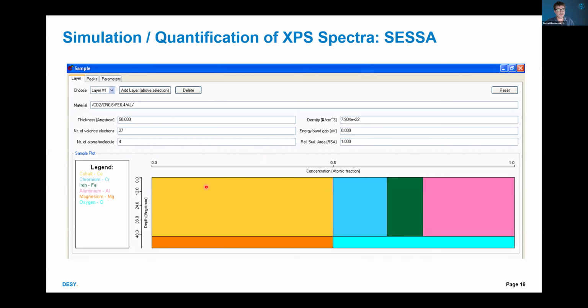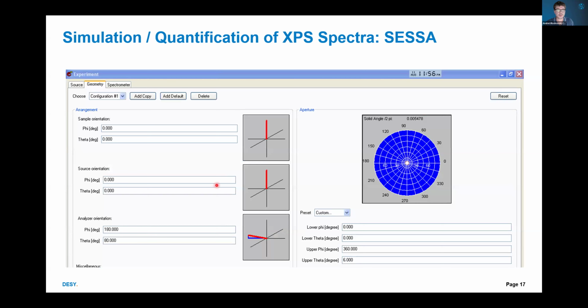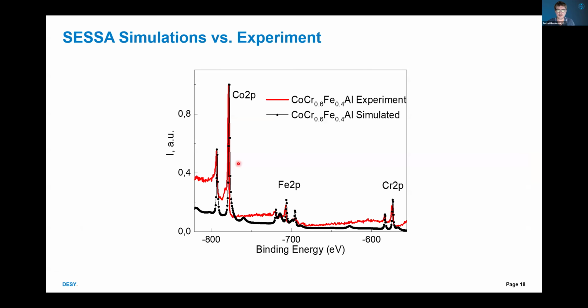As I told, the software, I think SESSA, is now freely downloadable from the NIST website. You can simulate very well the shape of the photoelectron spectra. You can define the composition of your sample, in this case cobalt, chromium, iron, aluminum, and then the substrate. Then you define the geometry and excitation energy, and you get the black curve, the simulated spectrum. So you more or less know what you expect to see during the experiment, if you want to come prepared, or if you don't have the possibility to pre-characterize your sample in your home lab.